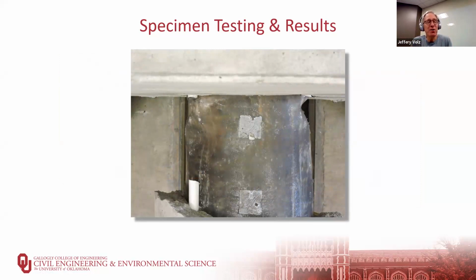If it were to, you would place a hoop compression stress because you're trying to push material into a smaller diameter. If you test steel tubes under compression, if you've looked at any other testing, you'll see they buckle both inward and outward and not in the same location. So they might buckle inward on the two opposite sides and outward on the other two opposite sides. That's the least energy state. But that concrete is confining it. So you get really a three-dimensional buckling state. This is how the concrete confines the steel from buckling. That is at a much higher energy state, much more capacity.